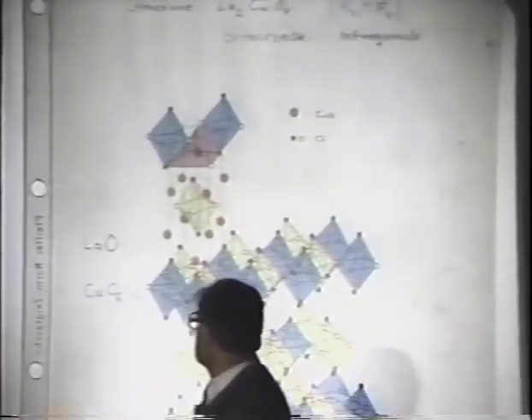Now, the structure which we found is this potassium nickel fluoride 4. It's a layer structure, but this structure is tetragonal, whereas the one we have is slightly orthorhombic. What you have is sheets of copper-oxygen 6 octahedra, and in between you have layers of lanthanum oxide. And these octahedra are now not in a plane, but slightly tilted along 1, 1, 0 directions if you don't substitute the lanthanum by, say, barium or strontium, an alkaline earth metal ion.